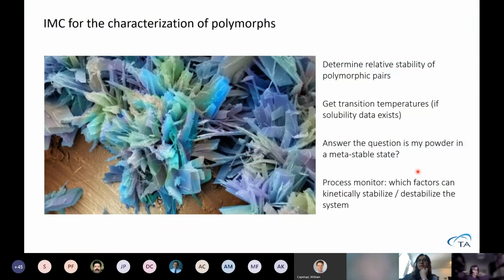And how would you use microcalorimetry to characterize this? Well, we can use microcalorimetry to determine the relative stability of polymorphic pairs. If we have solubility data from another test, we can get transition temperatures. It could also tell us if the powder is in a metastable state, that it's transforming over time, and we can also see which factors could stabilize or destabilize the system. So it could be used as a process monitor to watch what's going on with the molecules or with the samples.